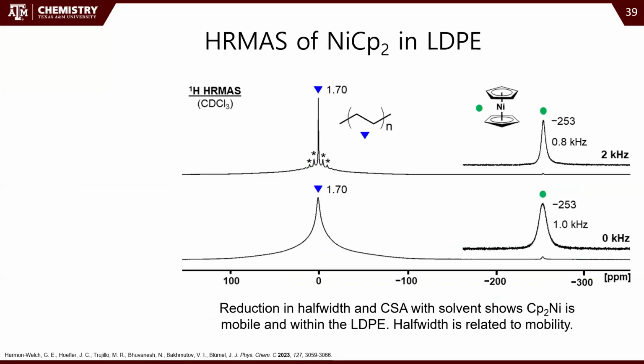And we did HRMAS, and so you can see that the nickelocene no longer has chemical shift anisotropy. It's just a single broad peak. And so that's telling us that it's being mobilized when there's solvent. So it is able to penetrate into the polymer network. And then when we reintroduce solvent, it's going into the solvent again. So we're kind of doing like rudimentary gel chromatography. If you have, for example, plastic that you want to recycle, this is something that you have to show. You can put in a material and take it back out. FDA has requirements on being able to show that you can pull out contaminants from a plastic if you want to use it in food or medical packaging.